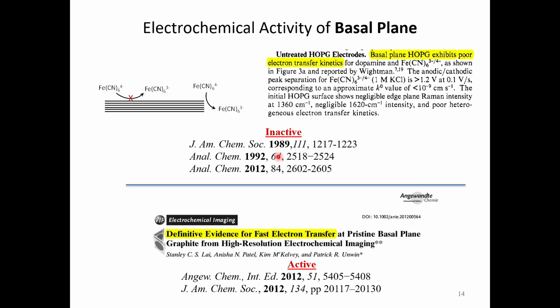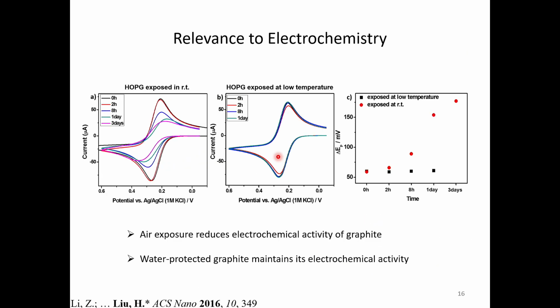So indeed, they expose their surface with a lot of hydrocarbon to begin with, even though they do not cover all the surface with hydrocarbon. But the presence of paraffin oil would produce a vapor that potentially would contaminate all the surface, even though it doesn't look like that's the case from their perspective.